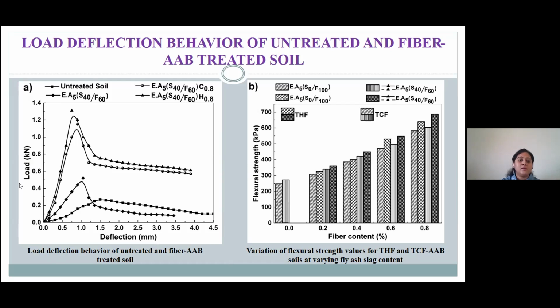You can see the load versus deflection curve reaches a peak and then drops. We also found the variation of the flexural strength with the soil at varying percentages of fiber content. This was published in one of the special issues of Journal of Geosynthetics and Ground Engineering.